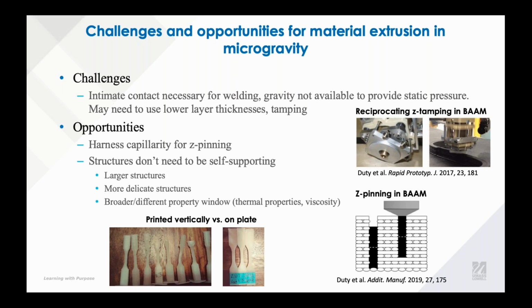However, there are some possible opportunities as well. So there has been some work in using Z-pinning in order to improve the Z strength in big area additive manufacturing. And since capillarity isn't bound by gravity under microgravity, then there's this potential opportunity to be able to harness that for Z-pinning more broadly. Another thing that comes up in microgravity is that we don't have this need for structures to be self-supporting because they don't need to deal with gravitational forces. So potentially we can have larger or more delicate structures that are being printed. And then also, there's a broader property window where we can start thinking about materials that have different viscoelastic or viscoplastic behaviors because they don't need to be self-supporting. So you don't need to worry about slumping quite as much. Next slide.